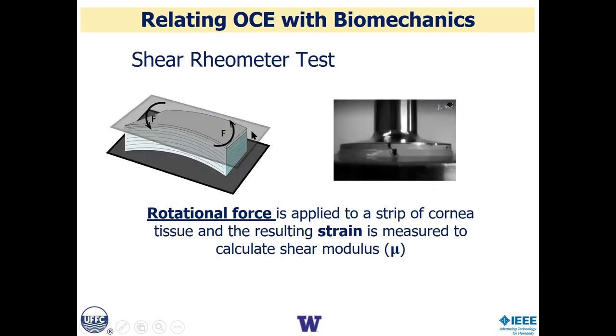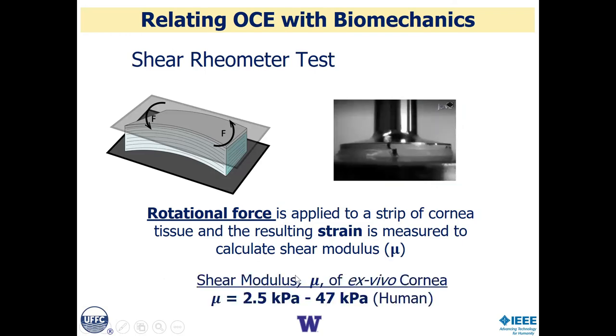The second kind of test, which is done destructively, is direct shearing tests, which is rheometry or torsion, rotational force. And this is a direct measure of the shear modulus mu. And when you do that in cornea, you find this in the tens of kilopascals. So think around 30 kilopascals. So 3 megapascals for E and 25, 30 kilopascals for mu.